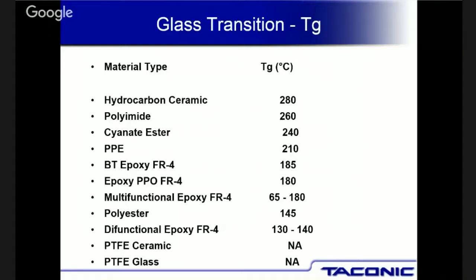So we always put in there NA, not applicable, because if we put down the real number that you get from all these DSC tests and different types of testing, the number sometimes scares people away from using it because they say it's very low. But again, it doesn't melt, so it doesn't flow, so we don't have an issue with the T sub G, actual TG temperatures on Teflon materials.